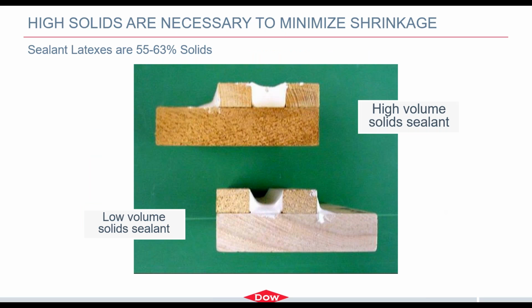The other thing I mentioned was solids of the polymer. Higher solids are very desirable to minimize shrinkage. Typically, the polymers in our portfolio range anywhere from 55 to 63% solids. Once it's formulated into a sealant, this is an example of a high volume solid sealant where you get some shrinkage, but it's pretty minimal, and that is quite a stable view. Whereas down here in a low solids sealant, you can see much more concavity, much more shrinkage, and this is a less desirable feature because it leads to more stress in the sealant.